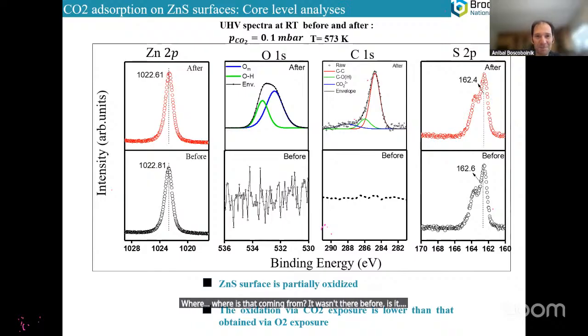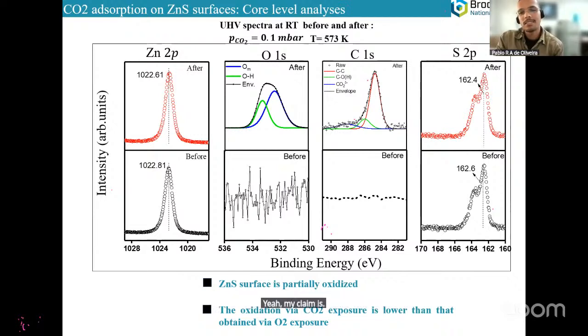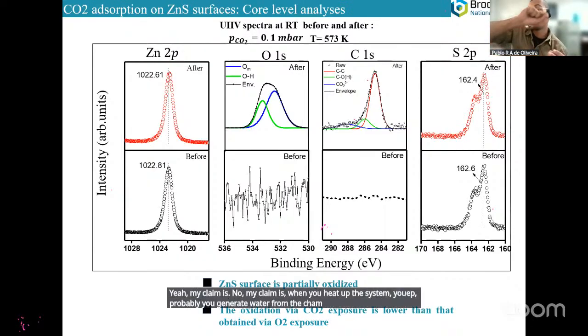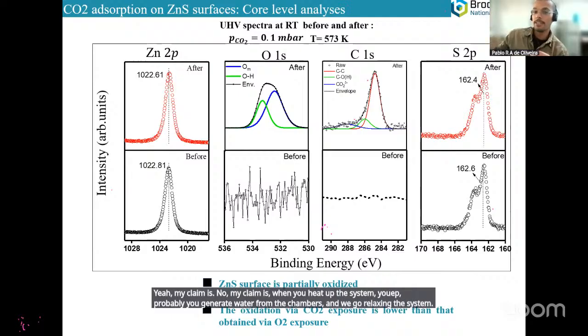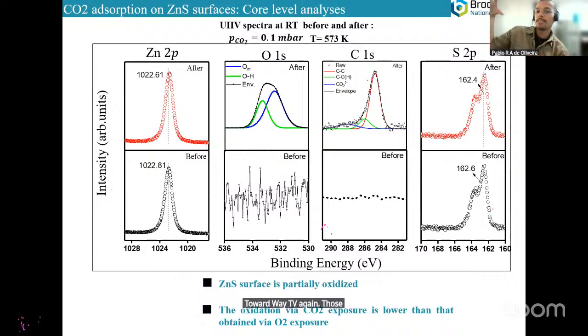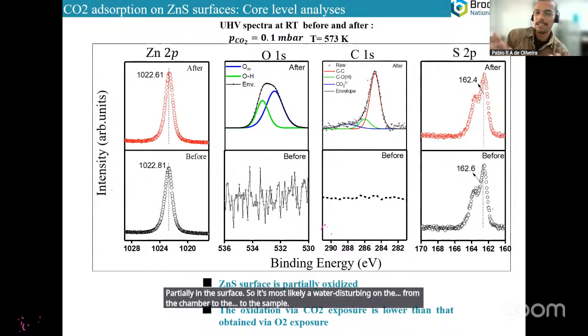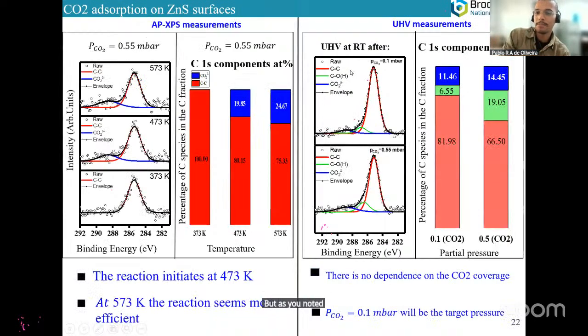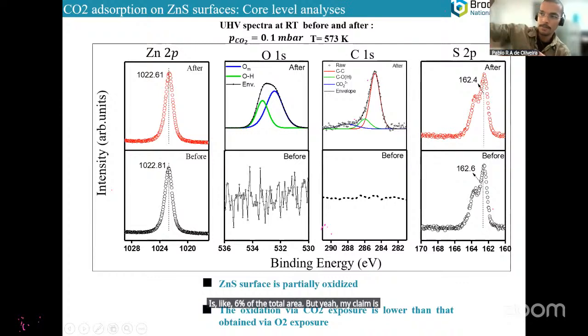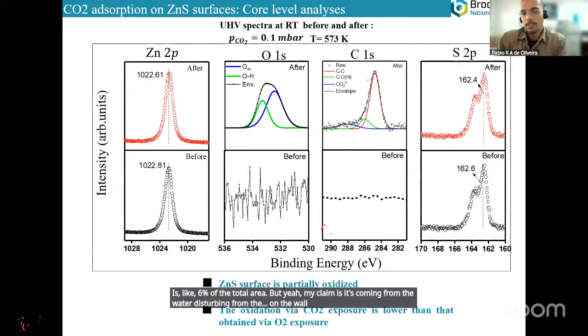My claim is that when you heat up the system at UHV, you probably generate water from the chamber walls as the system relaxes toward UHV again. Those water molecules in the chamber just stick partially on the surface. So it's most likely water dispersing from the chamber to the sample. But as you noted here, it's not that much at this condition, like 6% of the total area. My claim is that it's coming from water dispersing from the walls of the chamber.